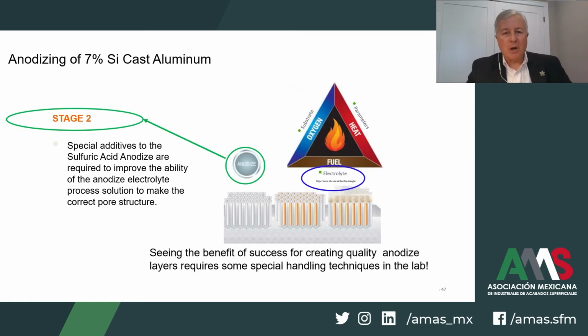One of the initial problems in the development of a successful process for anodizing the cast alloys was our ability to actually see the differences with the pore structure. So we've had to develop some specific techniques to be able to see in cross sections how the pore structure formation changes with these additives' inclusion into the sulfuric acid anodized solution.